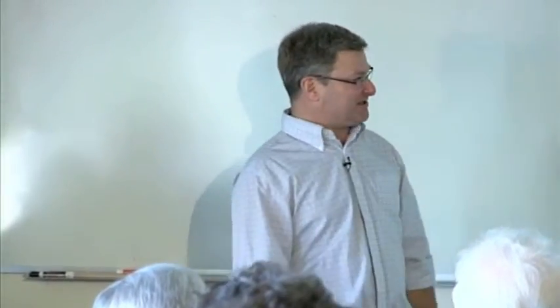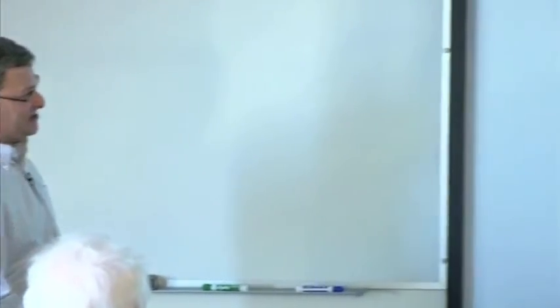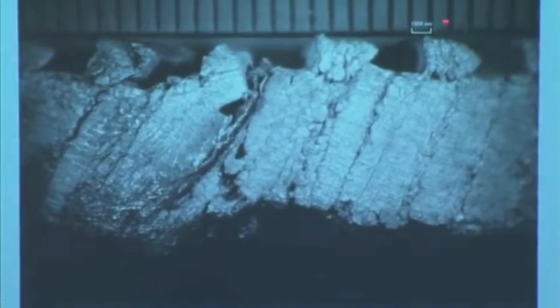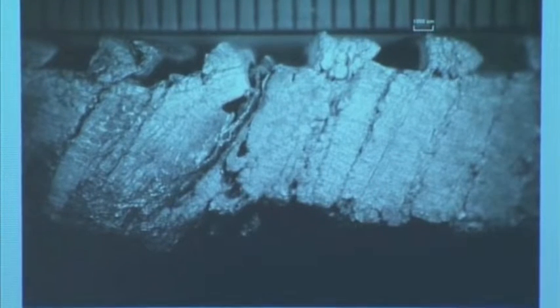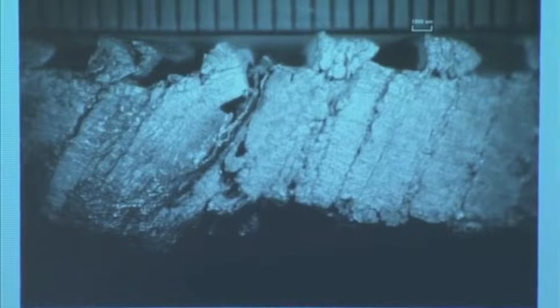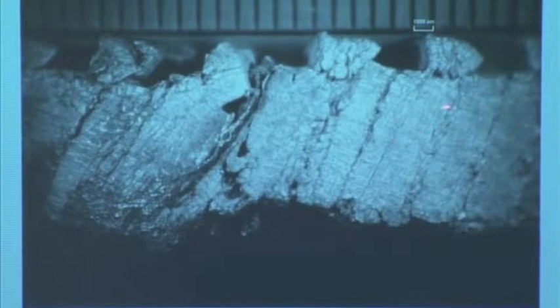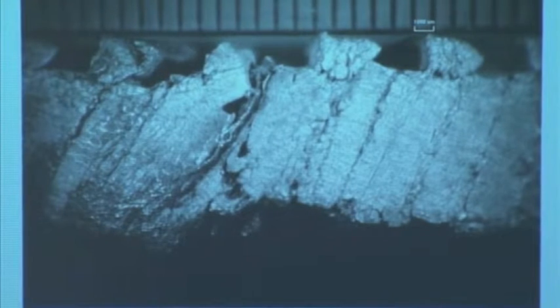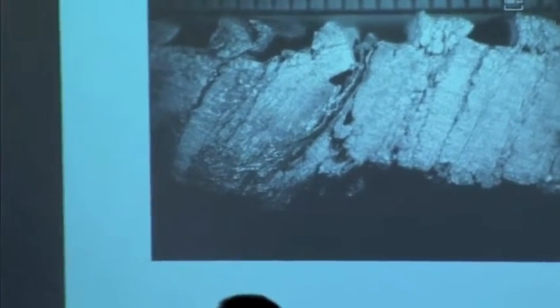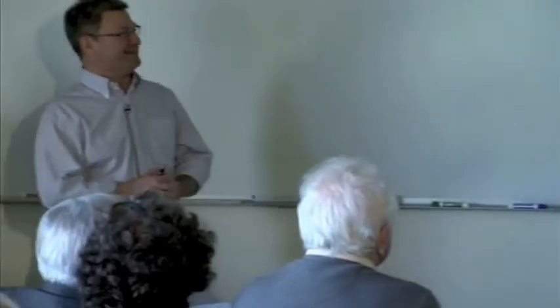All right. So this is a sort of picture of the things that we get. You can actually see those columnar crystals. And this is just a photograph. These are millimeter markings here. Under a microscope, you can also see the residue of those dendrites as well. But what you're looking at here are the crystals. This is a foil marker that you can show the deformation. This one actually was not deformed that much. Some of them we deformed quite a bit more. After we do this, we then perform metallography on the samples, and we look at it under an electron microscope to do crystal orientation work.